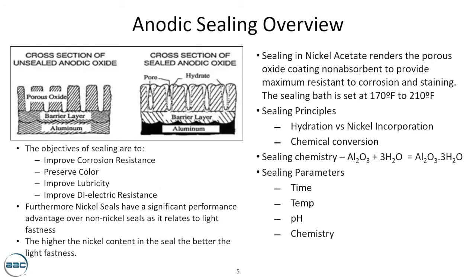All right, so the anodic sealing process is essentially two steps at its most fundamental level. One, you are filling that porous oxide layer with an active ingredient, in this case, nickel for most sealing processes. And then that step is followed by a hydration step. So you'll see in the image here, your porous coating, looked at from a cross-section perspective. That pore is filled with, in this case, nickel, and then hydrated.